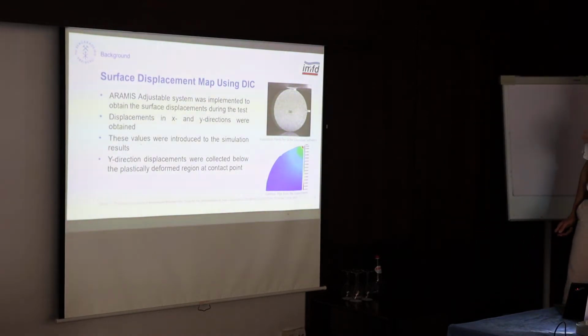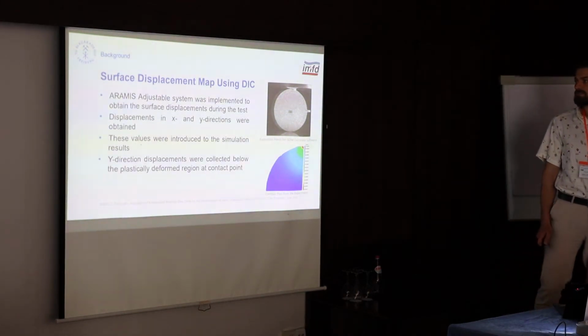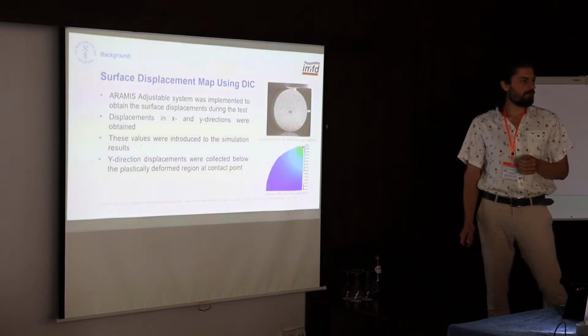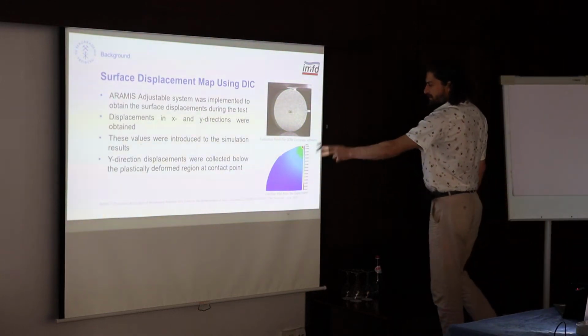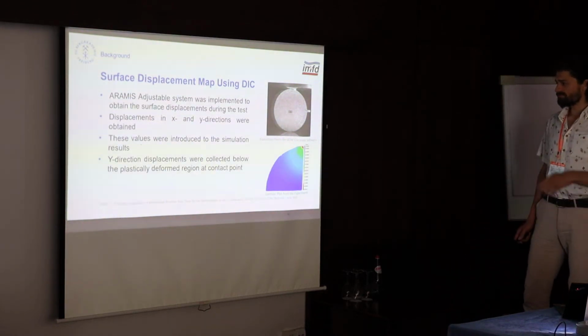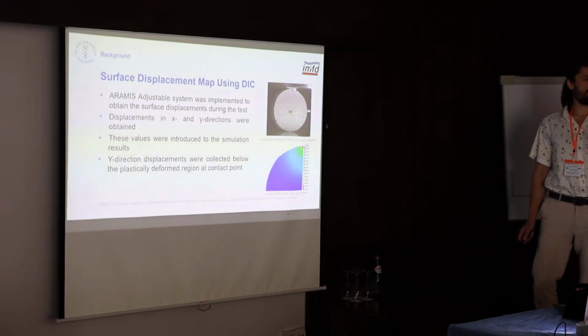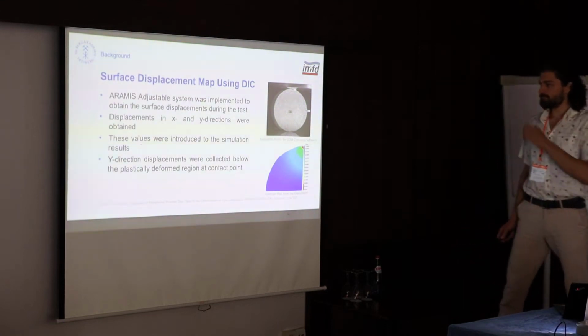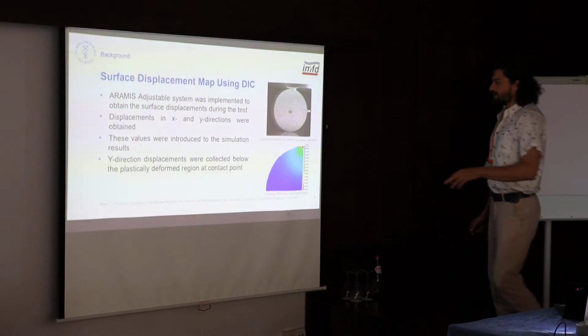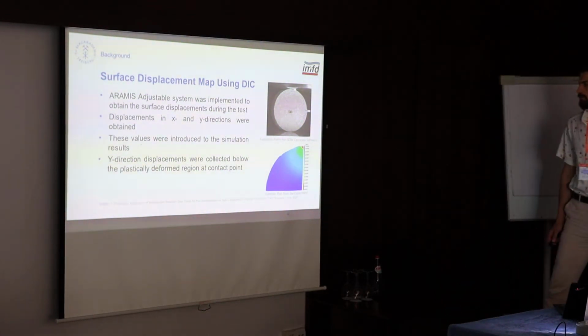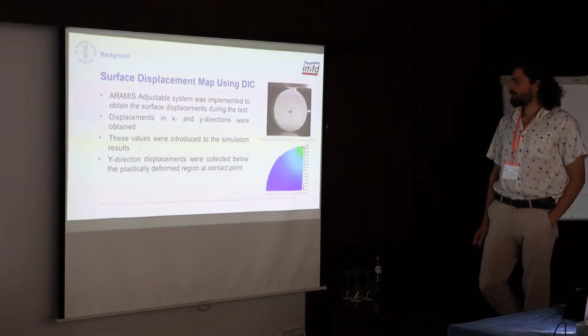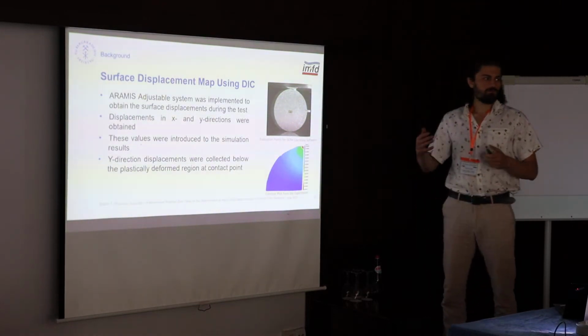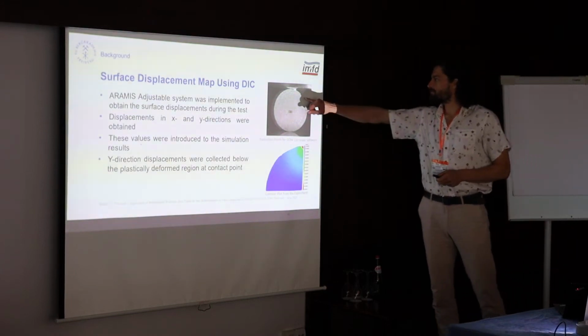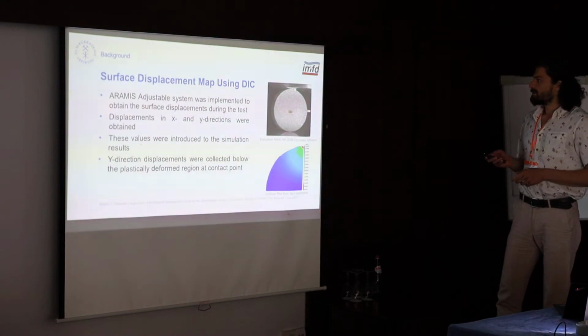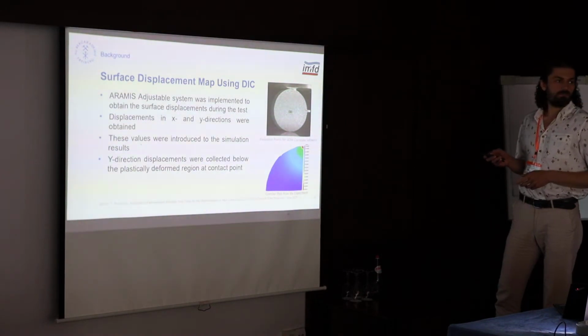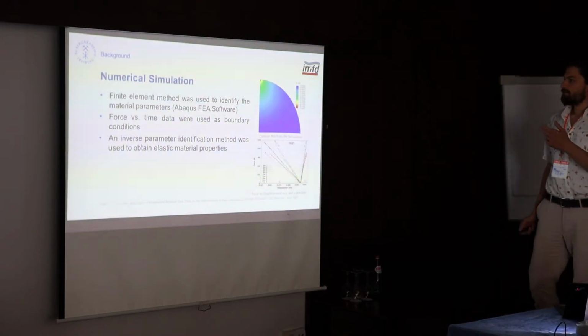So to begin with, I used digital image correlation using the Aramis system to obtain a displacement map throughout the test, which gives me this contour plot from the experiment, which later I introduced to my simulations so that I can do a parameter identification. So also you can note that there is this plastically deformed part at the contact region of the round specimen. So here what I did, for example, to just do my simulations with elastic parameters, I was able to collect my displacement in y direction only below the plastically deformed region, and later I made my